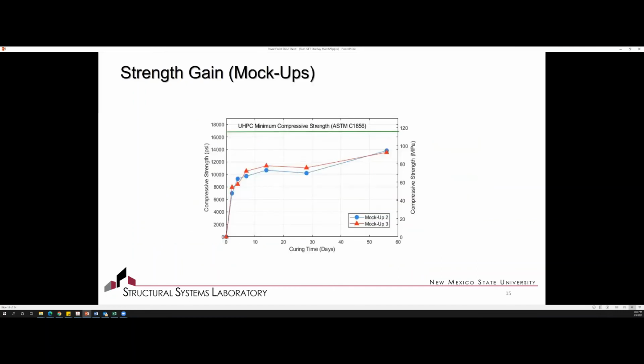Right. And then we also looked at strength gain. So I'm just showing the compressive strength gain, but we also looked at modulus of rupture and a few other properties of the material. And here you can see, as Dr. Wrighty and Dr. Floyd both mentioned, that the definition of UHPC is typically about 17,000 PSI or greater. When we had to make the change to the fibers, we had to give up some of that strength, which we were okay giving up, but because of that, we're a little bit lower than that definition of the UHPC minimum. So you can see our strengths are about 14,000 PSI right now on the mock-ups.